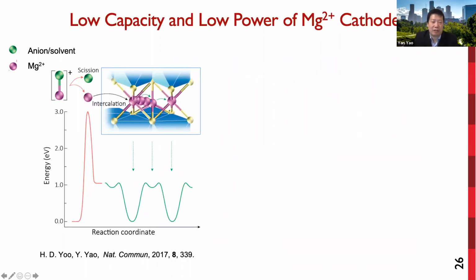So a major challenge for magnesium battery is the lack of efficient cathode material. So magnesium ions have twice the charge of lithium, while they have similar ionic radius. So magnesium cations are more polarizing than lithium. So as a result, magnesium dissociation from electrolyte solvent, or desolvation of its ions, needs to overcome a huge energy barrier like this. Furthermore, after this desolvation or dissociation, the intercalation into the cathode also needs to overcome a high energy barrier because of strong Coulombic interactions.